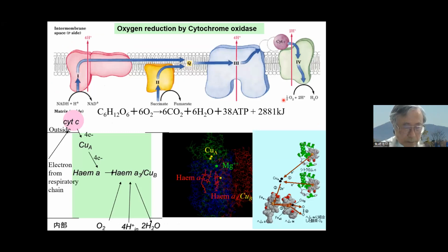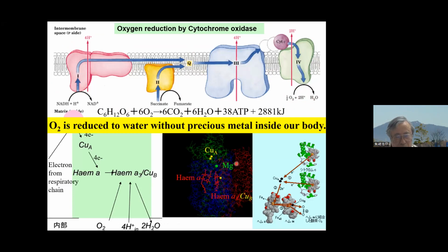Now, oxygen reduction is carried out in our body every second. We eat something, then it is oxidized by oxygen to generate CO2 and water and ATP and energy. At the end, cytochrome c oxidase reduces the oxygen to water. In our body, we don't use platinum. We just use copper and iron, some magnesium, something. So O2 is reduced to water without precious metal inside our body. Maybe it is interesting to see how many liters of oxygen we are reducing per day. You can calculate it easily based on the calories, and you know how many calories we are consuming. But anyway, it is interesting to see. Actually, it's quite a lot.